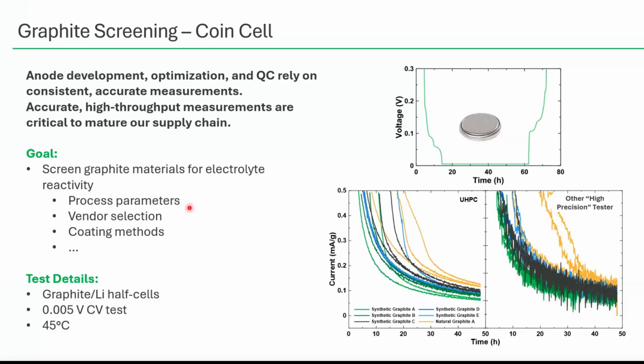So we're looking at screening these materials for electrolyte reactivity, and we're going to do this first just like we do a cathode in coin cells. You can see that compared to other high precision testers, there's both an improvement in the accuracy and the precision of the data you can get with these voltage hold style tests, where you're directly measuring, after all of the kinetics kind of even out, the parasitic current happening, the rate of those reactions.